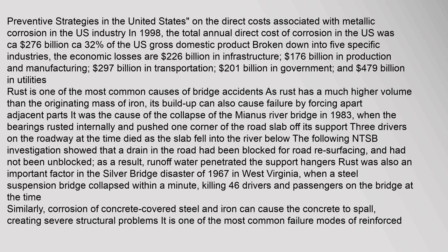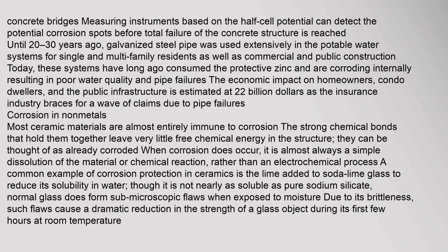Similarly, corrosion of concrete-covered steel and iron can cause the concrete to spall, creating severe structural problems. It is one of the most common failure modes of reinforced concrete bridges. Measuring instruments based on the half-cell potential can detect potential corrosion spots before total failure of the concrete structure is reached. Until 20 to 30 years ago, galvanized steel pipe was used extensively in potable water systems for single- and multi-family residences as well as commercial and public construction. Today, these systems have long consumed the protective zinc and are corroding internally, resulting in poor water quality and pipe failures. The economic impact on homeowners, condo dwellers, and the public infrastructure is estimated at $22 billion, as the insurance industry braces for a wave of claims due to pipe failures.